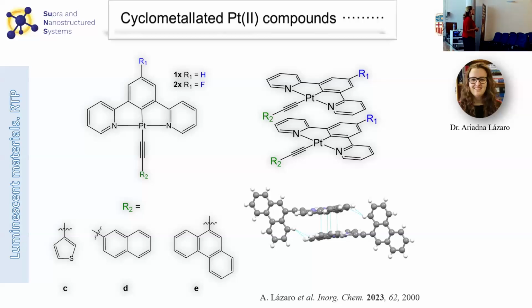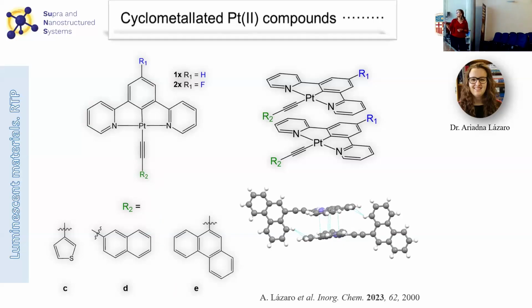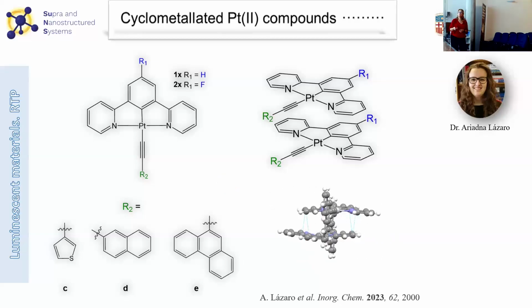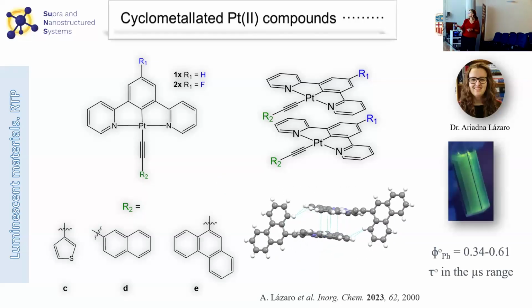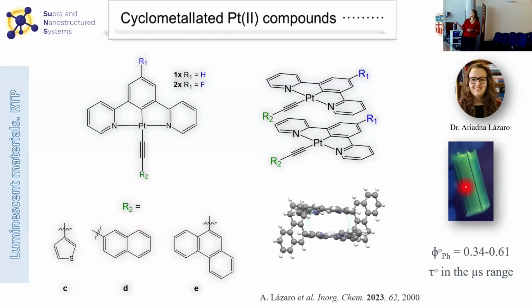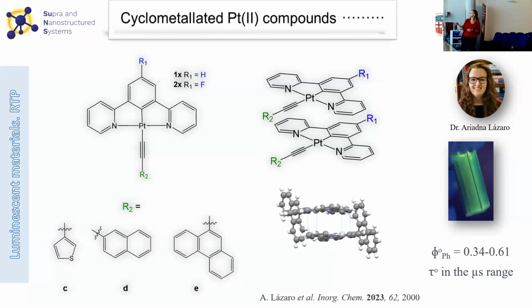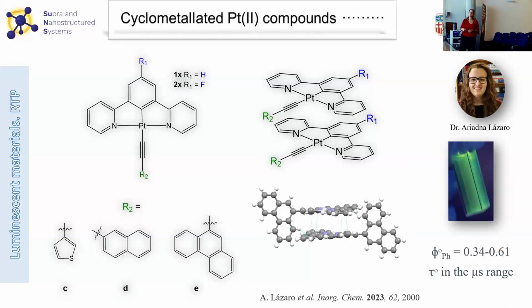So this was with gold, but I have also selected an example with platinum. So this was the work by Ariadna. In these cases, having room temperature phosphorescence is much easier. And she synthesized these compounds with an NCN ancillary ligand, also with different chromophores at the 4th position. She could also grow single crystals that indicate the formation of some pi-pi stacking and also metal-metal interactions. And in all cases, we can have pure room temperature phosphorescence with emission quantum yields up to 60%, so quite good.